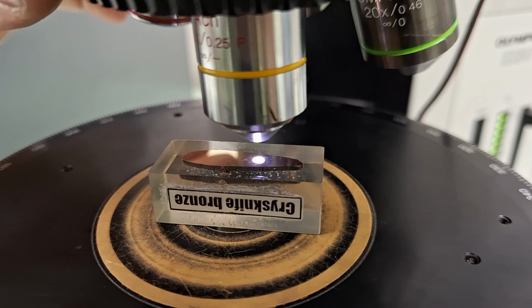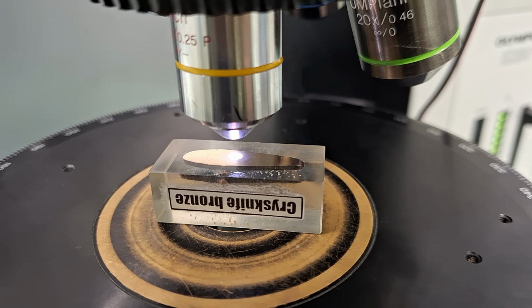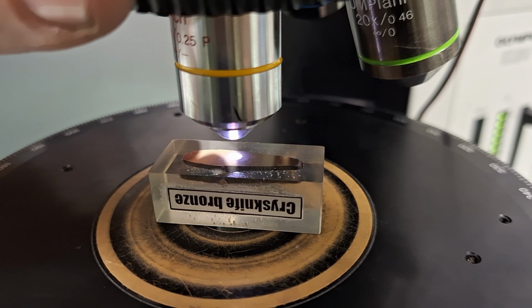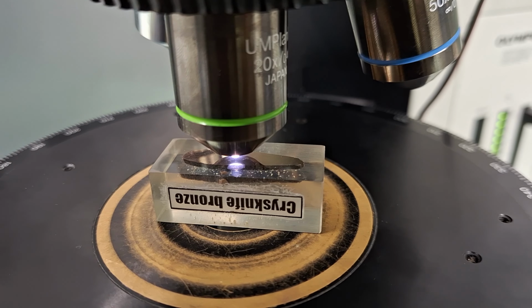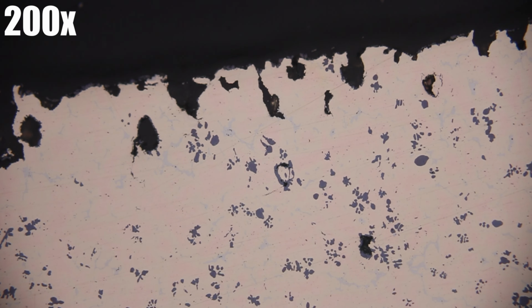Now let's switch to higher magnification. It is clear now that there are some dark gray grains present. As we reach 200 magnification, there is much more to observe. Besides the copper grains and those dark gray grains, there's also some bluish material.